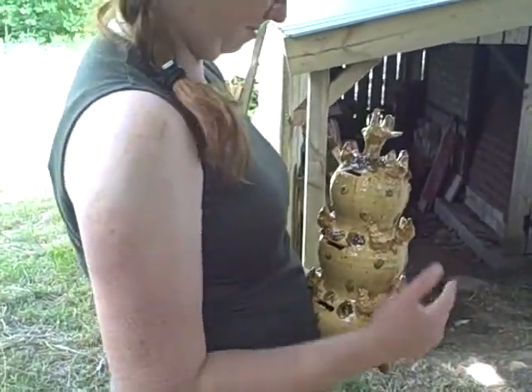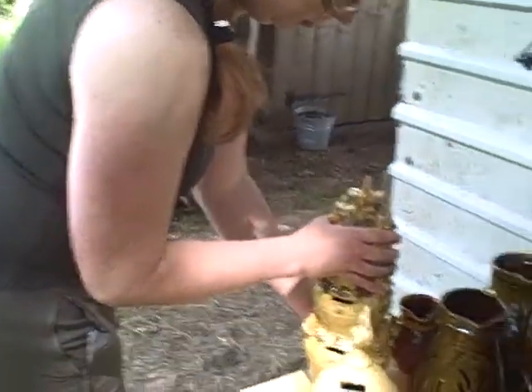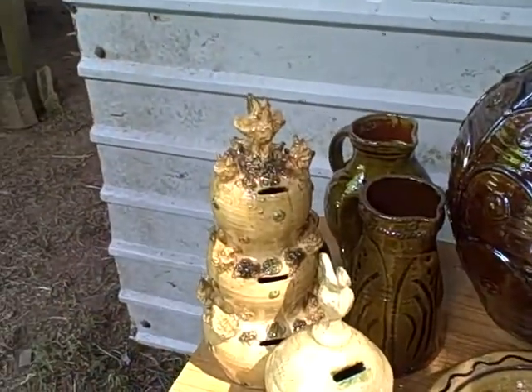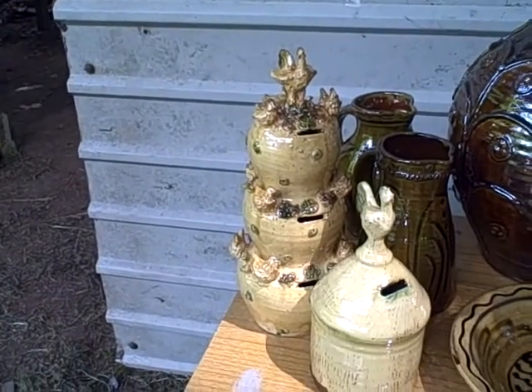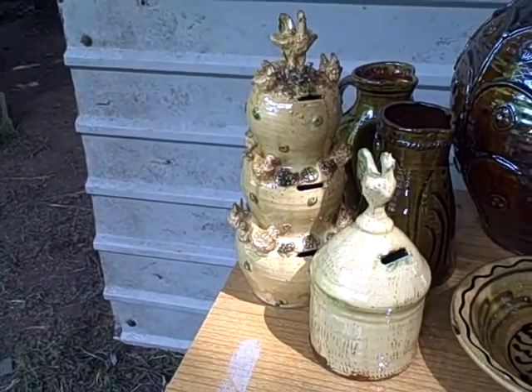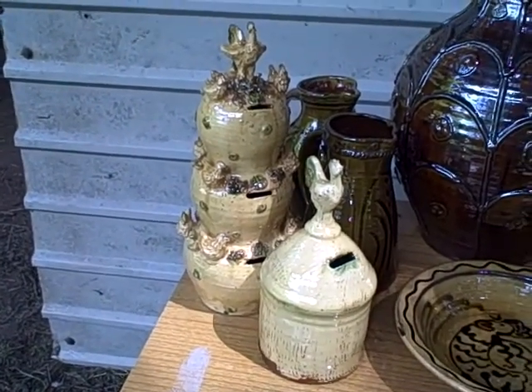This is based on one of the old country pottery money boxes that they used to have — three separate chambers for pounds, shillings, and pence. Got the glaze on it a bit thin and it's mighty under-fired, so I might go with a spot more glaze and pull it back through. Or I might just bury it in the ditch.